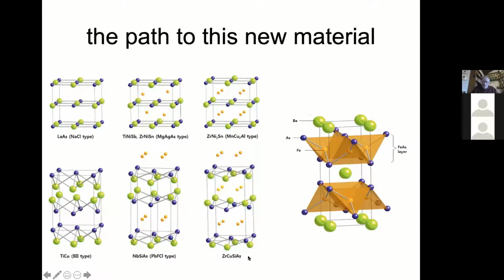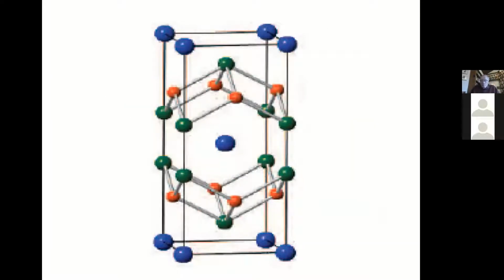superconductivity bonanza started. And related to this material is the fact that in the thorium chromium 2 silicon 2 structure shown over here, you have the same kind of transition metal pnictide layers that exist in this structure. And so a lot of the research on these materials has been done in this rather simpler structure, thorium chromium 2 silicon 2. But it's also interesting the fact, of course, that cerium copper 2 silicon 2, the original heavy fermion superconductor, is in this structure. So this is just another ball and stick picture of this thorium chromium 2 silicon 2 structure.